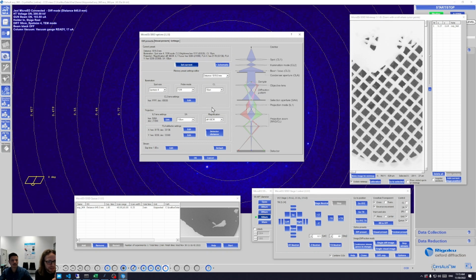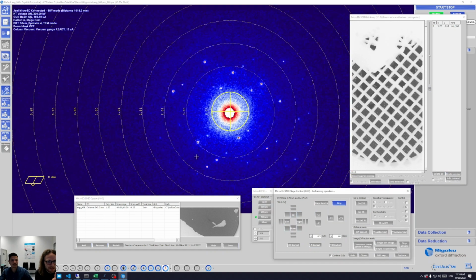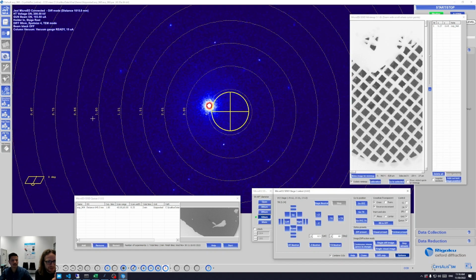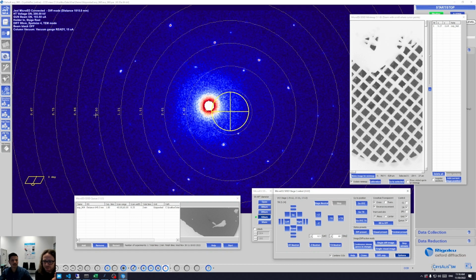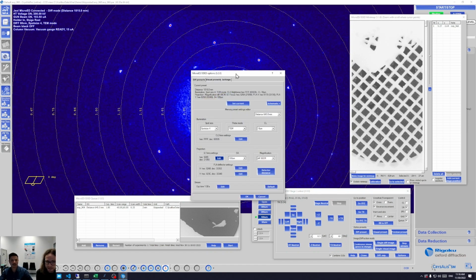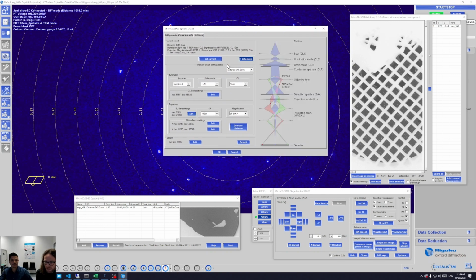And now if Kai closes that box, you will see something interesting happening, namely that you have the same diffraction pattern, but we just virtually moved our detector away, so we zoom into the diffraction pattern. For this diffraction pattern, this is a relatively pointless exercise because it was actually pretty well matched to the detector distance we had set before. But now suppose you want to measure, let's say, a framework material with a long unit cell or even a protein, then this becomes an absolutely essential feature.